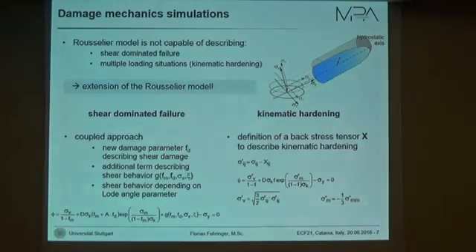The problem is, the Rousselier model is not capable of describing shear dominated failures, so small stress triaxialities, and multiple loading situations, because it's missing a kinematic hardening claim. So in our work we have to do at least two extensions. First, to describe shear dominated failure, we are looking for a coupled approach by introducing a new damage parameter describing the shear damage and adding a term describing the shear behavior, which will depend on the Lode angle parameter. For kinematic hardening, we will define a backstress tensor which describes the kinematic hardening effects and which will influence the stress tensor we use for our Rousselier model.